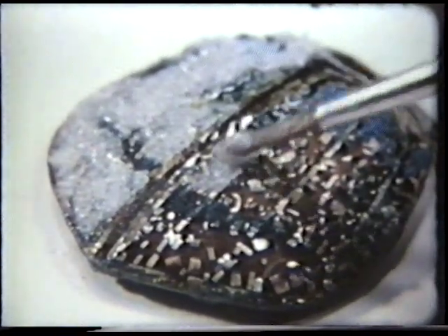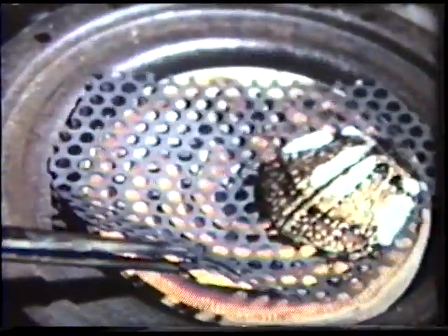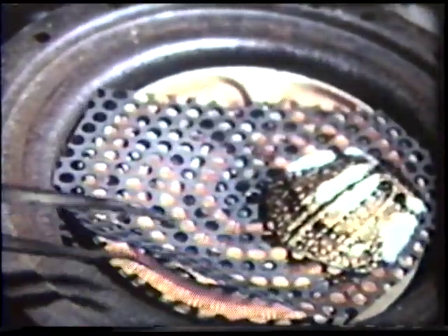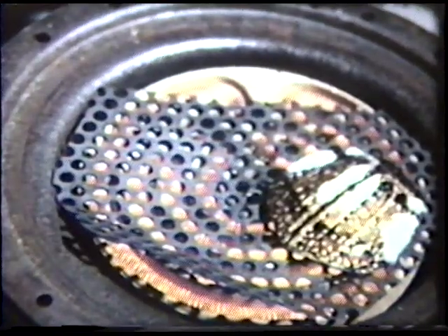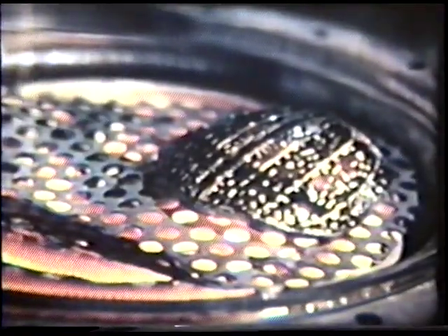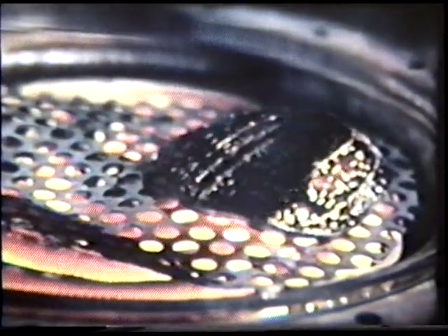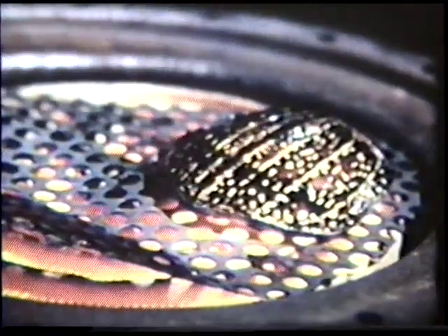Another firing, a clear, transparent flux and a strong blue are added over the previous coat. In this film, to avoid repetition, several of the firing sequences have been eliminated. Finally, areas of opalescent blue are applied to depressions that have been left for it. The enamel has now reached a height slightly greater than that of the cloisons.